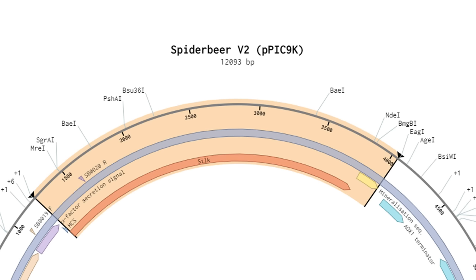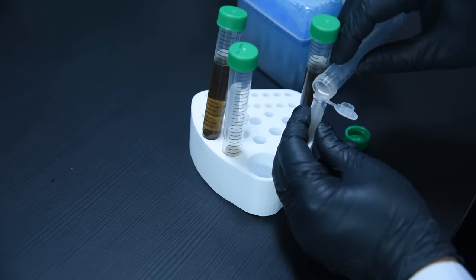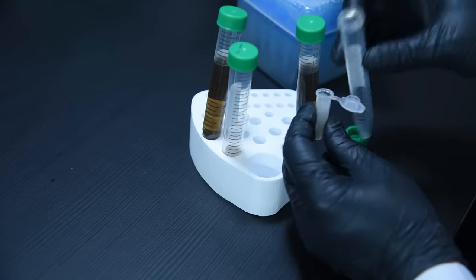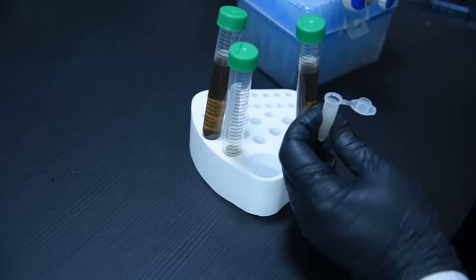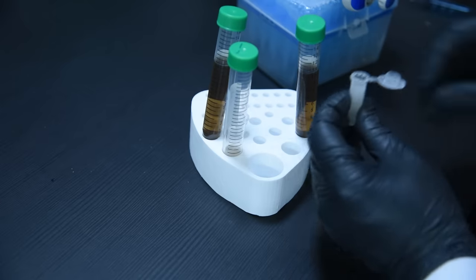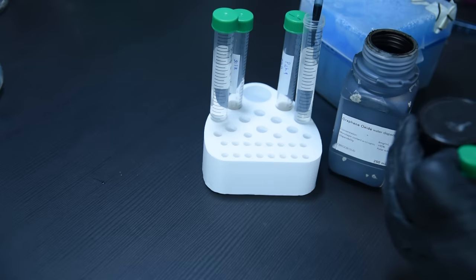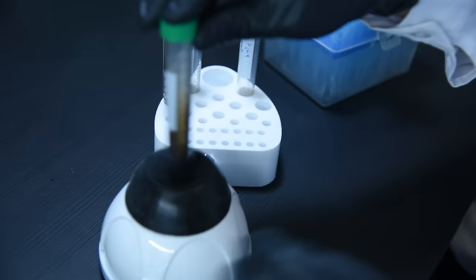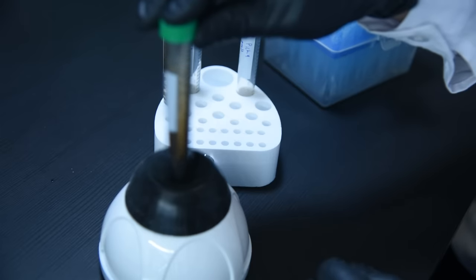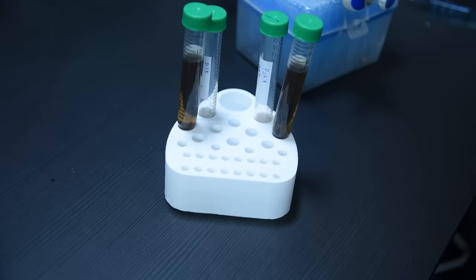One last test was to directly see if the silk is working as intended. I grew two tubes of yeast, one of the original Pichia, and one theoretically expressing the silk proteins. I collected the goop at the bottom of each tube and resuspended it in 2 milliliters of plain water. Then I made a solution of graphene oxide in water. Normally, graphene oxide is stable in solution, and with a quick mix, you can see that it disperses very easily.